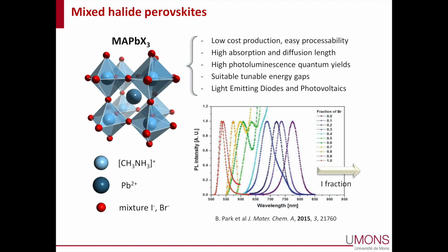In those systems, what you can do, so you see here the structure with the octahedral configuration of the lead halide. You can change the composition going from either pure iodine to pure bromine. And it's also a nice way to tune the emission properties, as you can see from this graph, going from purely bromine to purely iodine. You get a strong redshift in the photoluminescence peak across more or less the entire visible.